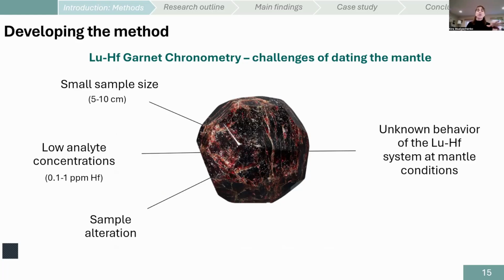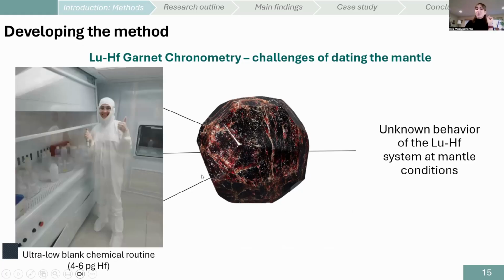So all of those challenges lead to the biggest challenge, the unknown behavior of the lutetium-hafnium system at mantle conditions. You may ask why, since we have been applying it so successfully to the crust. Well, because most of the isotope geochronology relies on the concept of closure temperature that is tied to the cooling rates and is tied to the temperature itself. And as you know, the temperature in the mantle is way higher than what we have in the crust. And the concept of a cooling rate is not really applicable to the rocks that are sitting at 1200 degrees for billions of years. So the first three challenges can be overcome with careful lab work.